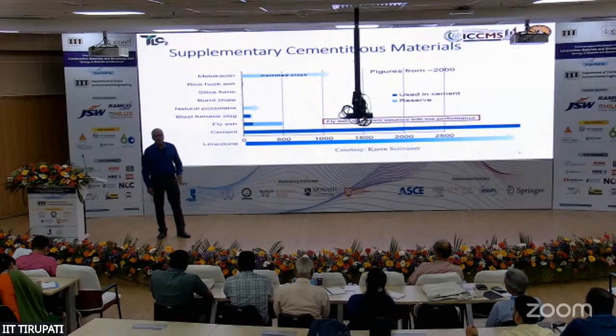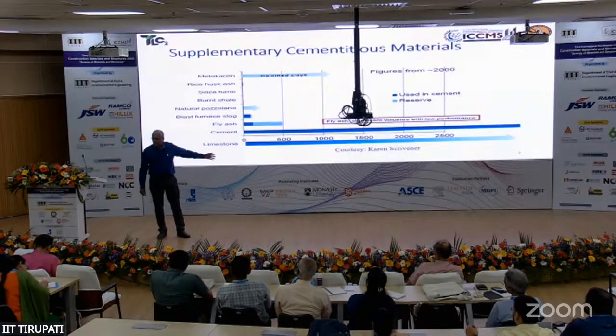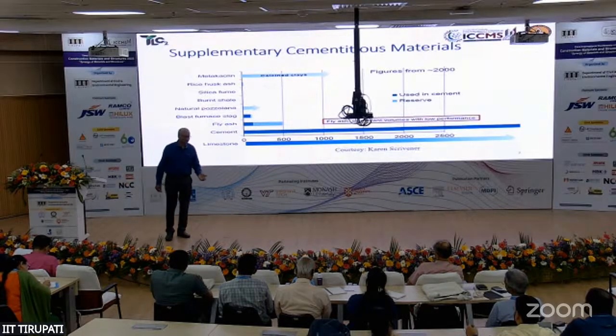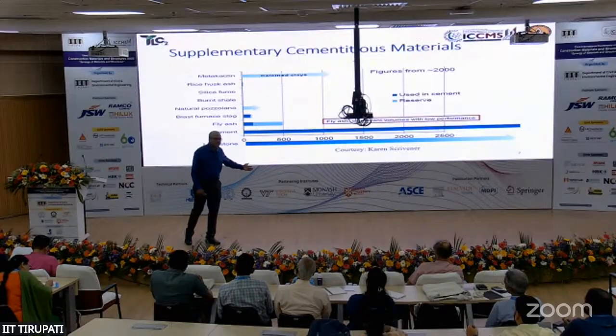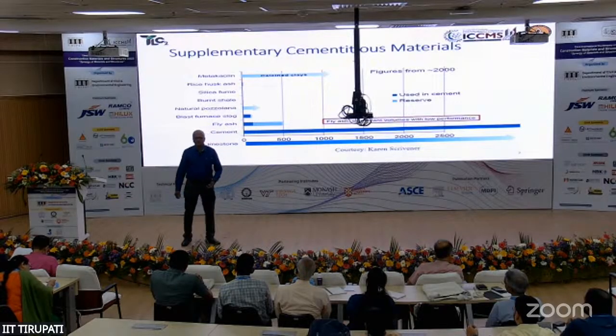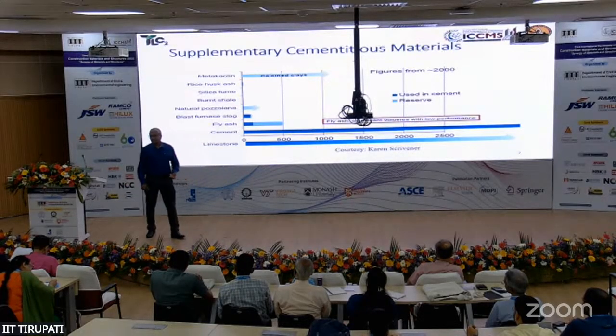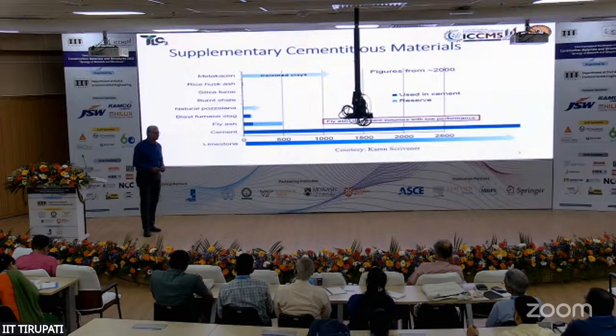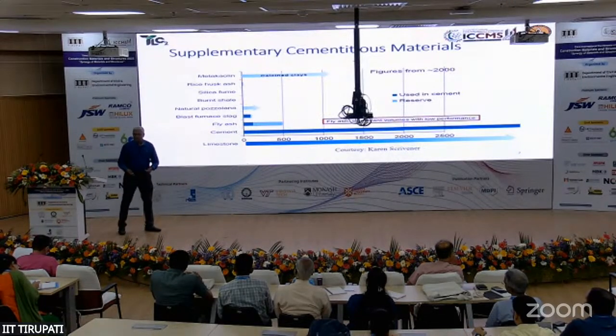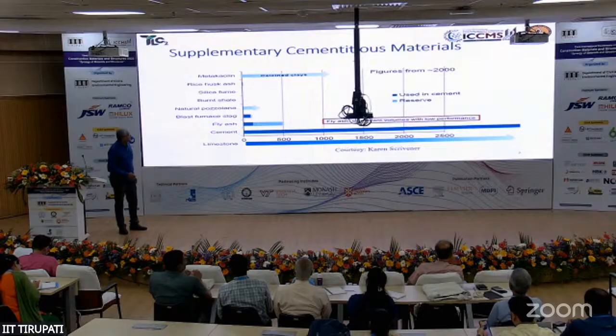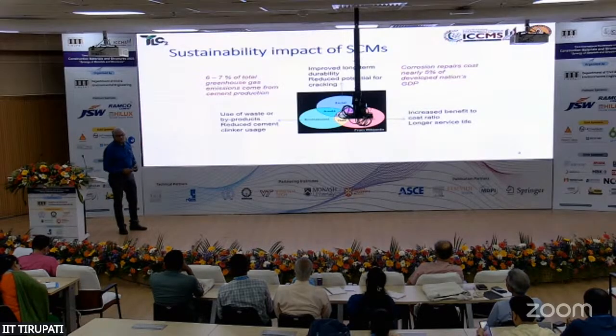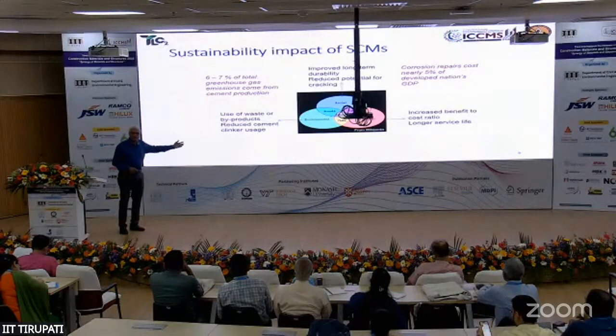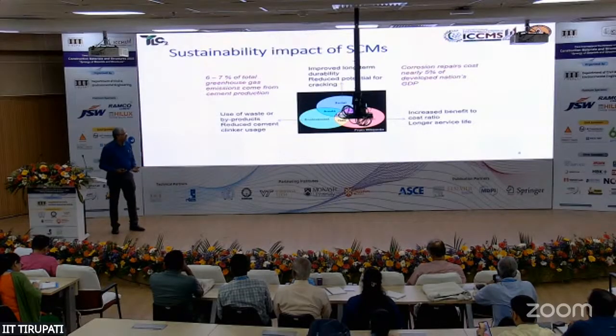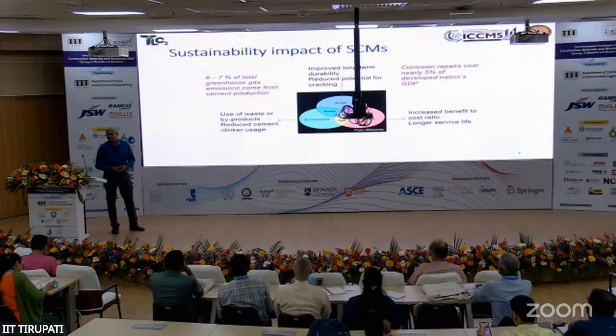Why do we need to do all this? It's been estimated that, at least in India, if we utilize all the available limestone to only produce Portland cement, then our limestone reserves, which are good for cement manufacture, may not last beyond 50 years. So you have to look at finding replacement materials, and that's probably the best way to think about why we need to replace cement. And of course, from a sustainability perspective, use of mineral additives is definitely a positive thing, because you are reducing the utilization of cement clinker, which leads to a lot of CO2 emissions.